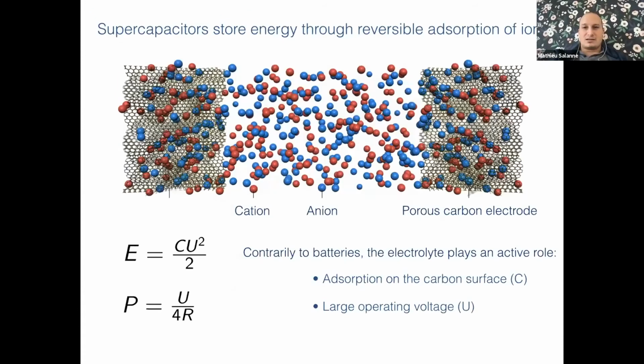So how do these devices work? They are much simpler than batteries because everything is based on physical adsorption. You have 2 electrodes, which are porous. Here you have porous carbon, which is the most used material. When you apply a voltage between the 2 electrodes, you start to accumulate ions from the electrolyte on the 2 sides. So you will enrich in cations on one side and anions on the other side. All the energy is stored at the electrolyte interface in the region that we call the double layer. There are 3 quantities which are important: the voltage of the device, U here, in the energy and the power density; the capacitance, which is an interfacial quantity; and the resistivity, which is mostly linked to the conductivity of the electrolyte, so it's quite easy to tune.